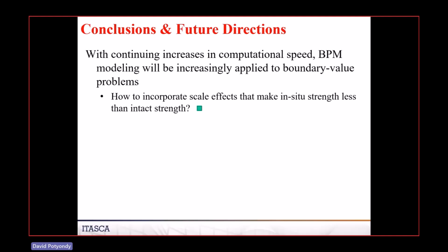What we found is that we constructed a PFC 2D flat jointed material. We were able to show that we could match the tensile strength and the UCS and the increase of strength with confinement. And we then built a series of those PFC materials where we had smaller particles and smaller particles and smaller particles, and we were able to show that we got the same UCS and the same tensile strength. And so for those properties, we were independent of particle size.